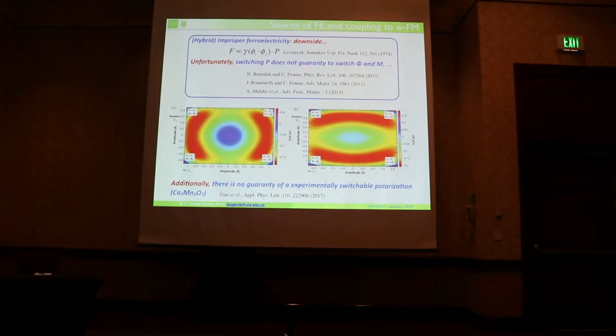However, there is a downside to this. The only downside that we have seen up to now is that there are plenty of switching paths. Therefore, there is no guarantee that switching the polarization will switch the mode that tunes the magnetization. As we can see, for example, in this figure from this paper, you can switch the polarization but leave the magnetization untouched.